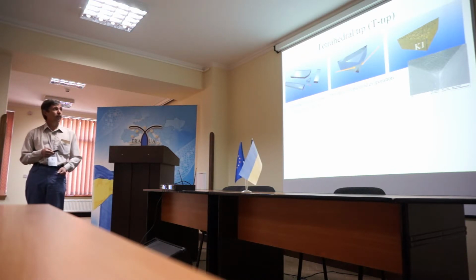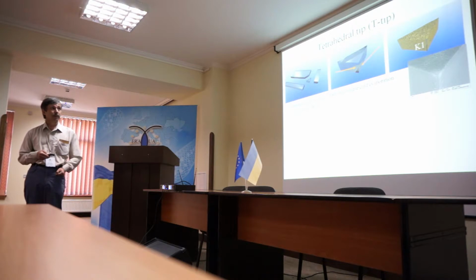Because if we break the glass, the edge of the break is very sharp. If we do it twice, it produces this corner. The radius of curvature of this corner is about 5–10 nanometers. After that, it is covered by metal.